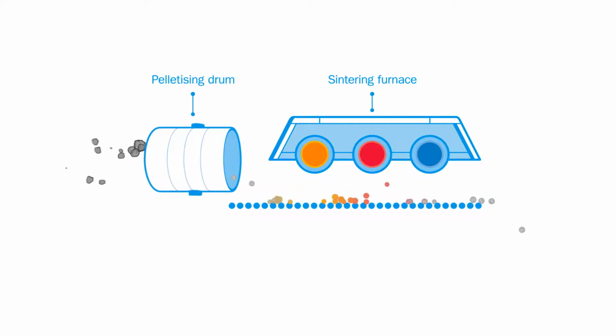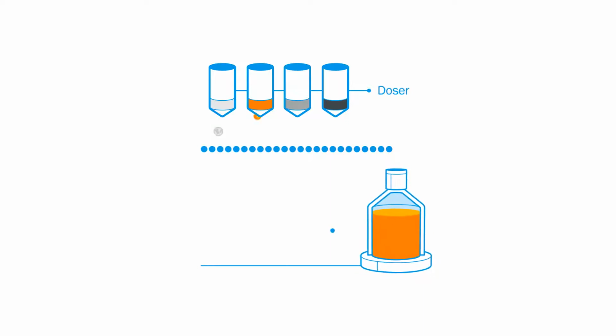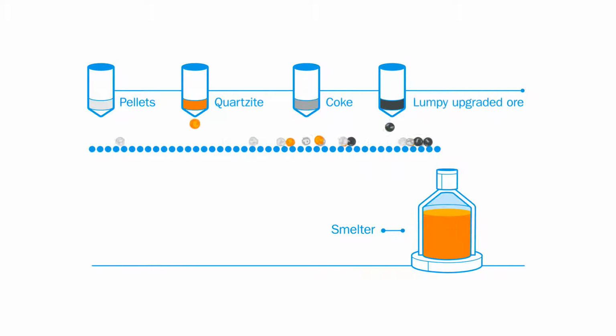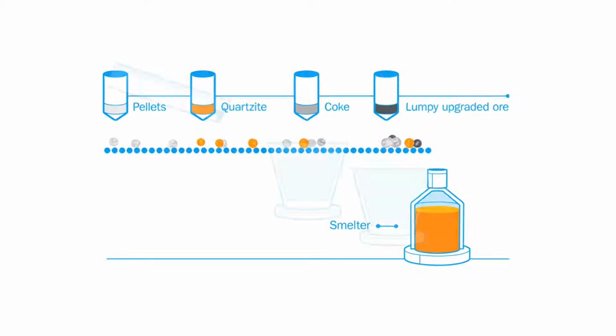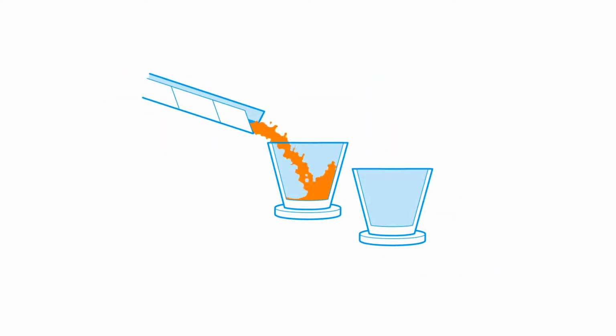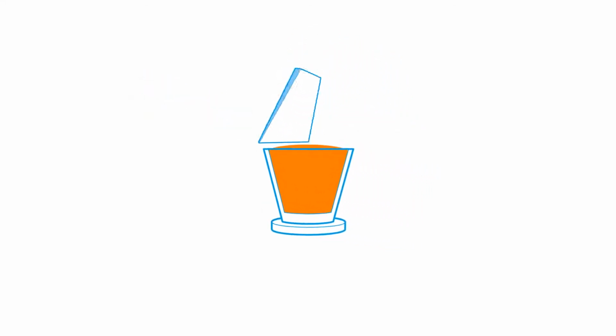Fine concentrate arrives from the Kemi mine and is mixed with bentonite and coke dust and fed into the pelletizing drum. The pellets are then fed into the sintering furnace. After sintering, the chromite pellets are ready for use. A dosing system charges the smelter with chromite pellets, quartzite, coke, and lumpy concentrate. After smelting in the furnace, the ferrochrome smelt is tapped into a ladle and the slag byproduct removed.